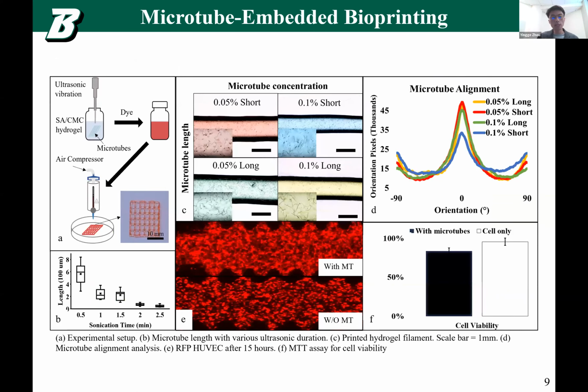And what's next is we break down these microtubes using ultrasonic vibration, and then incorporate them into the bioprinting hydrogel. So we have different lengths of the microtubes. For example, based on the ultrasonic sonication time, you can have an average 600 micrometer length of microtubes. You can also have just maybe 50 micrometer microtube length.